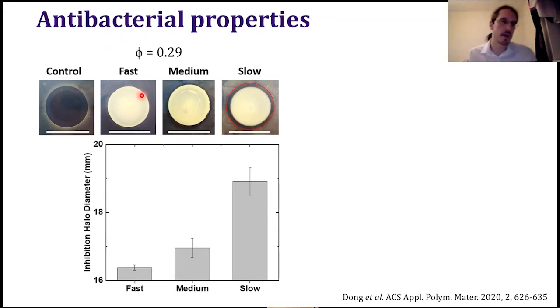And what we see is that for our control sample, which is the uncoated glass slide, this yellowish tint is all the bacteria growing all the way to the rim of the glass. But when we add our antibacterial coating, then we can start to see that there is a bit of a space in between the bacteria and the coating. So it's inhibiting the growth. And also for slow evaporation, it's even larger. So here you have what they call the inhibition halo diameter, which is just this diameter here. And you can see that for slow evaporation rate, this halo is the largest of all of them.